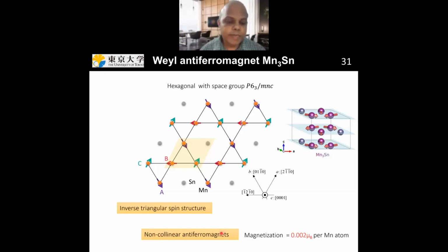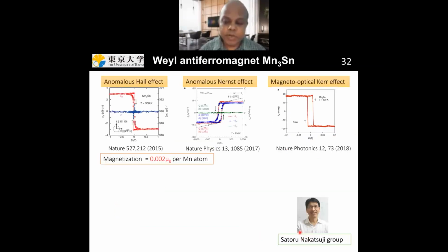So ideally one would expect that the total spin of this antiferromagnet will be 0, but we found that it has a finite magnetization moment, very, very tiny, 0.002 Bohr magneton per manganese atom. So this Mn3Sn was discovered in Satoru Nakatsuji's group where I was working. So what we found was that this is an antiferromagnet.